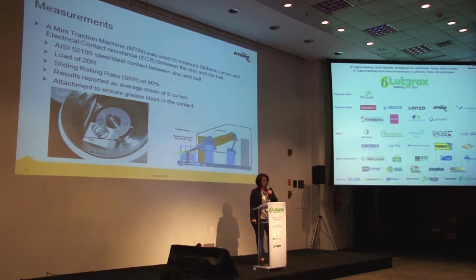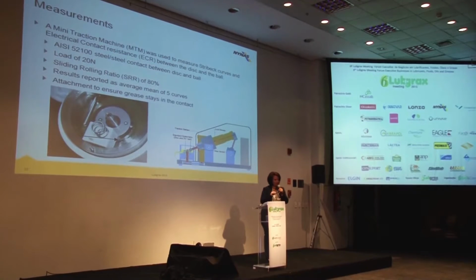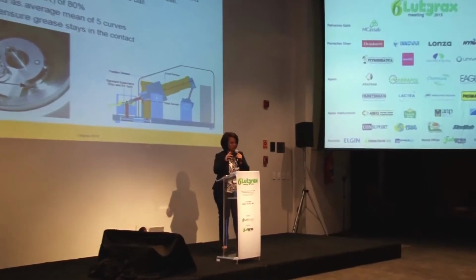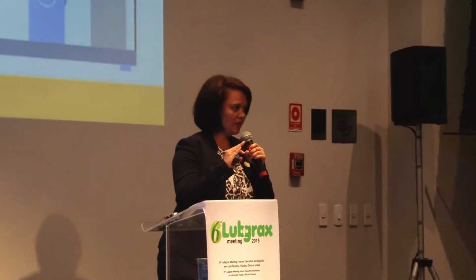We used a sliding rolling ratio of 80%, and that was determined experimentally, as this is a ball on disc setup. So if the ball is supposed to be rolling, it will not roll 100%, but at some point it might slip or slide. So you try to determine the optimum slide to roll ratio, and then you can set your instrument accordingly to get acceptable results. We ran 5 runs and took the average of those.